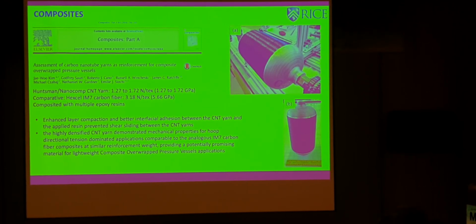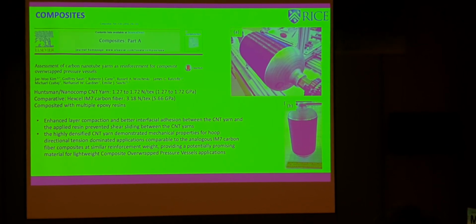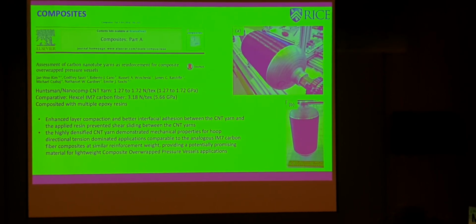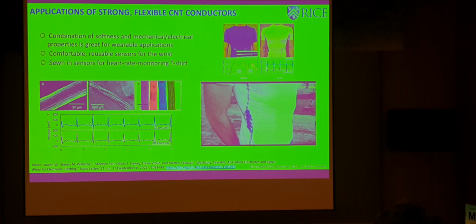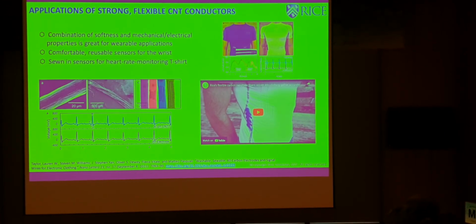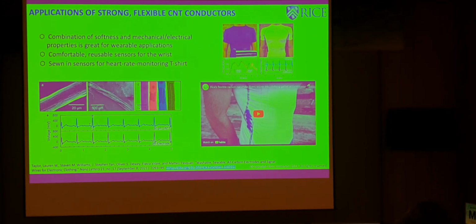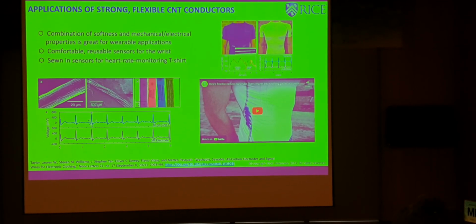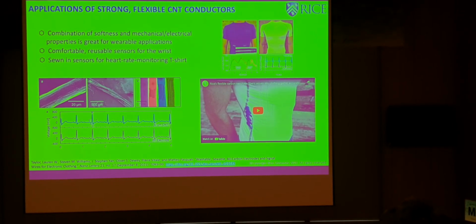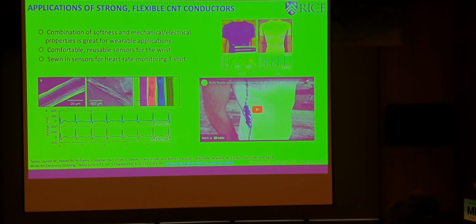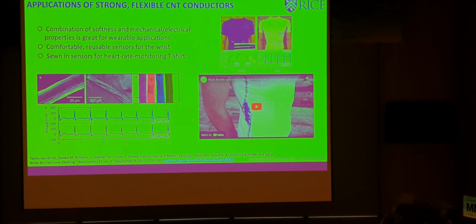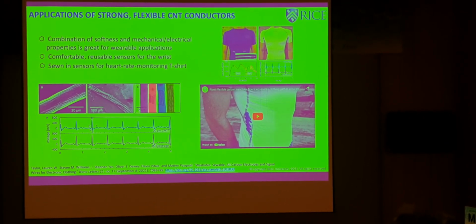But what Mia observed is that even though this yarn was not as strong as the IM7 fiber to which it was being compared, once it was made into a composite tank, it had analogous performance. This is from my group where we looked at wearable electrodes. So there was another thing that was not quite expected. When you put these fibers in contact with the skin, they make very good electrochemical contact, and so you can get the heart rate, or you can actually get a medical quality EKG, and you can sew these fibers onto tissues, which again is something that Nanocomp had seen at about the same time.